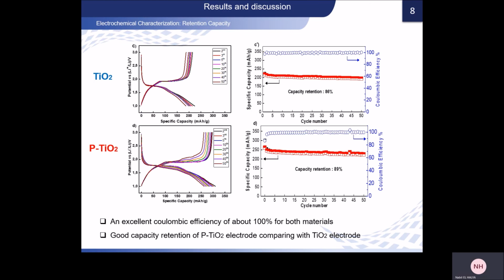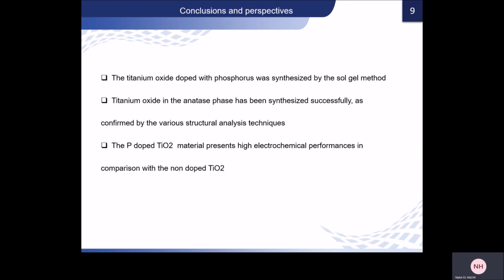This figure presents the Coulombic efficiency together with the cycle capacity profile for 50 cycles. So an excellent Coulombic efficiency of about 100% is demonstrated for both doped and non-doped titanium dioxide electrodes. Moreover, the capacity retention of the non-doped electrode after 50 cycles is only 86% and 89% for P-doped titanium dioxide. So these excellent electrochemical properties would be explained by the smaller particle size prepared by the sol-gel method that permits a more rapid lithium insertion and extraction process. So as a conclusion, the titanium oxide doped with phosphorus was synthesized by the sol-gel method.